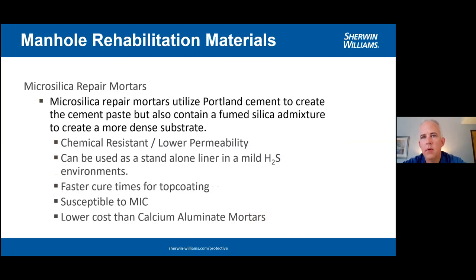So what my company, and what the majority of rehabilitation companies, recommend for rehabilitation is a microsilica mortar. Microsilica repair mortars utilize Portland cement to create the cement paste, but they also contain a fumed silica admixture that makes a much greater density of the substrate itself. It's a much lower permeability, much more chemical resistant substrate once we rehabilitate these things using microsilica mortars. In a very mild H2S environment, it can be used as a standalone liner. But what we generally use it for is putting protective epoxy coatings back on top of it.